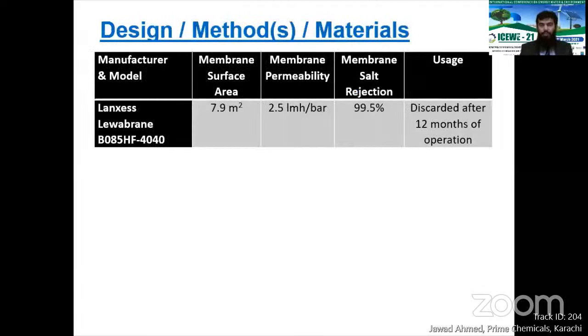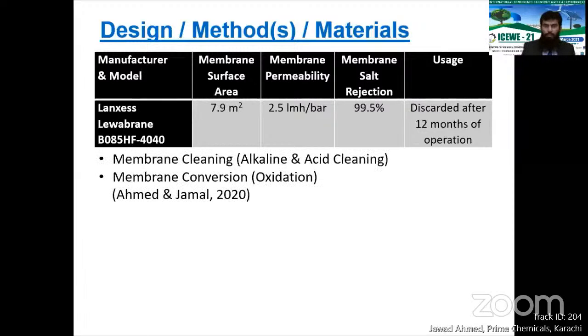So the materials and methods: the membrane that we have used is a Lanxess Lewabrane 4-inch diameter, 40-inch long RO membrane with a membrane permeability of 2.5 LMH per bar and a virgin membrane salt rejection of 99.5%. The membrane was discarded after 12 months of operation. After that, it was subjected to membrane cleaning in cycles of alkaline and acidic cleaning. This was followed by a membrane conversion process by exposing the membrane to sodium hypochlorite at 300,000 ppm-hours. The details of these materials and methods, and the results of the conversion process, have been published by our team last year.